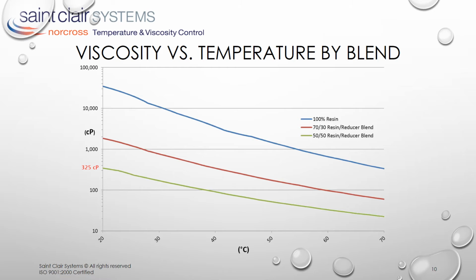The first is that the 50-50 blend is at 325 centipoise at 20 degrees C, or about 68 degrees Fahrenheit. Following our assumption then, we can hold the 50-50 blend at 20 degrees C and make a direct substitution in our process. But as with solvent-borne coatings, the goal is to minimize reducer to control cost and improve performance. Following to the right, we find that at 40 degrees C, the 70-30 blend is also at 325 centipoise.